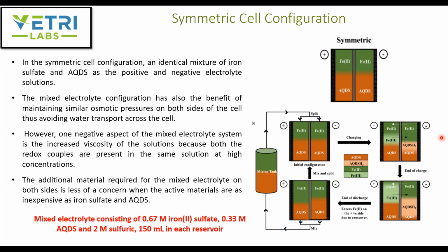So by doing this, when you do multiple cycles, if any imbalance arises in the distribution of the ions between the two sides, they have said that you can fix it by mixing the electrolytes and evenly splitting the solutions between the two reservoirs. At the end of charge, you have Fe3+ on the positive side and more Fe2+ on the negative side, but then the Fe2+ is going to diffuse, it's going to crossover onto the positive side. So at the end of charge and end of discharge, what you find is an excess of Fe2+ on the positive side due to the crossover. They've also identified that AQDS, since it's a larger molecule, has no crossover. So all the crossover studies are mostly focused on iron 2+ or iron 3+.